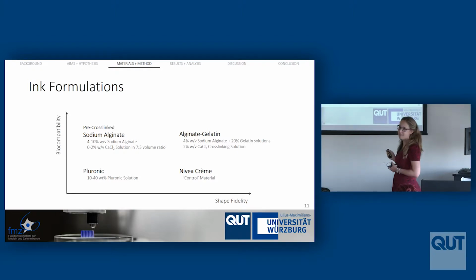And then it turns out Nivea cream, so your standard hand cream, is actually really, really great for bioprinting. So the photo I showed earlier was bioprinting with Nivea cream. It's got exactly the right rheological properties that we want for bioprinting, and so we use this as our control material. We compare all of our other bioinks to Nivea cream to make sure that that's what we're going to be able to print with. So very high shape fidelity, low biocompatibility. Putting cells into Nivea cream is not such a good idea.